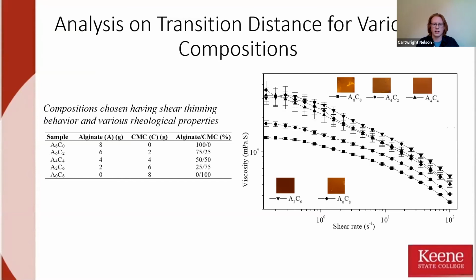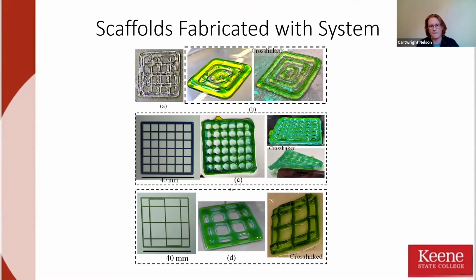So the materials used were alginate and carboxymethylcellulose. The CMC material is a thickening agent used to increase viscosity. And the alginate is really good because it's natural. It comes from seaweed, and it comes as a sodium alginate salt, which can be mixed with water to create the hydrogel. And since it's natural, it's very good for the cells. And it also is very rapidly cross-linkable with calcium chloride or other double valence salts like that. So that's really nice. You can see the cross-linking in the previous one, which basically adds structure and immediately solidifies the print so it can't just disperse all over like the top and bottom uncross-linked scaffolds.